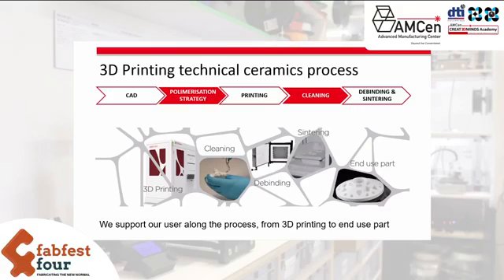So the first step is to do the CAD file of the part. Nothing special. Then the printer software will slice the part in order to indicate to the laser which area to cure at each layer. Then the printer will print the parts layer by layer from the bottom to the top. In fact, a blade will spread a thin layer of paste on the printing platform, and the UV laser based on the top of the printer will polymerize the area to polymerize.